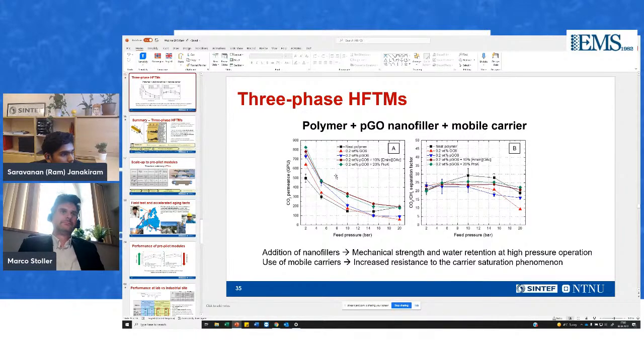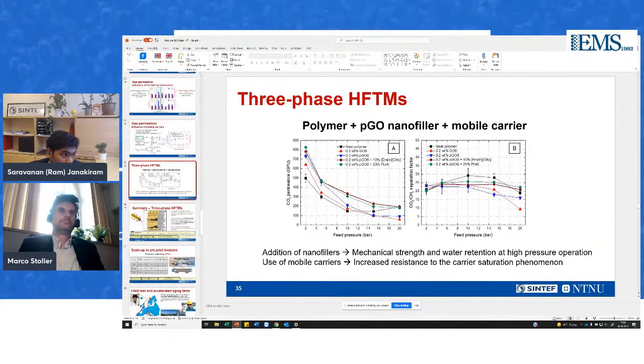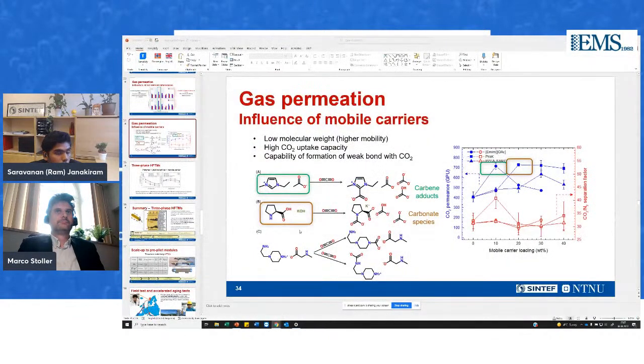So you have a system where ionic liquid was used as a mobile carrier, because ionic liquid as such is a small molecule, which means that you can use that as a mobile carrier. So we know that it's compatible with the system, which means that in this case, we added just the ionic liquid on the polymer, and we found out that this EMIM acetate has actually given us good performance at 10% loading. So for each system of mobile carriers, a different optimum was obtained because of the properties of the mobile carriers, the properties of the interaction between the polymer matrix and the mobile carrier, and, for example, the solubility of the mobile carrier. So in this case, it was quite interesting that we can add only 10% of the ionic liquid, and it was already helping us.